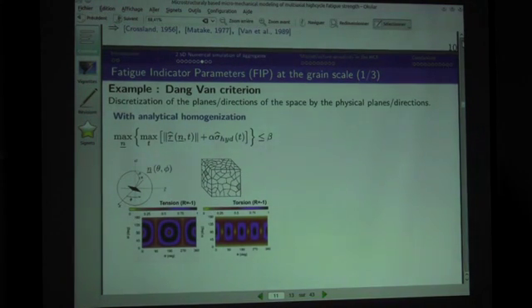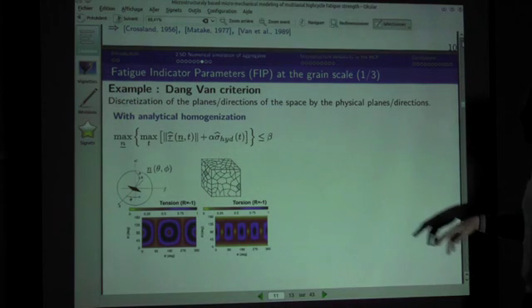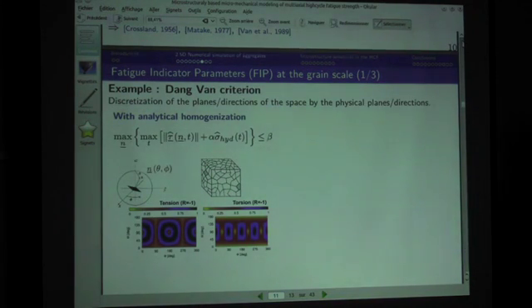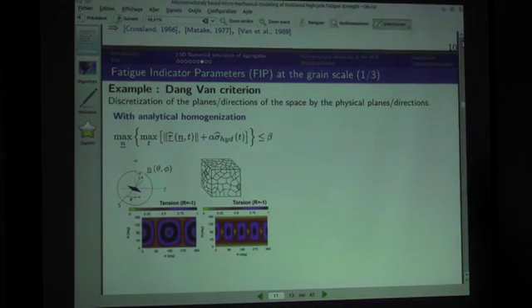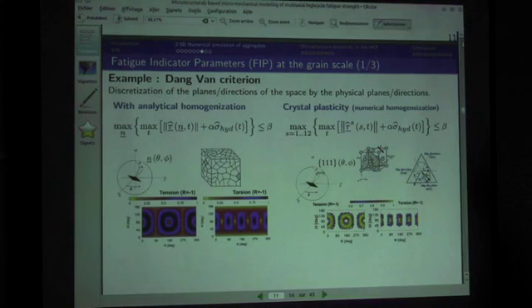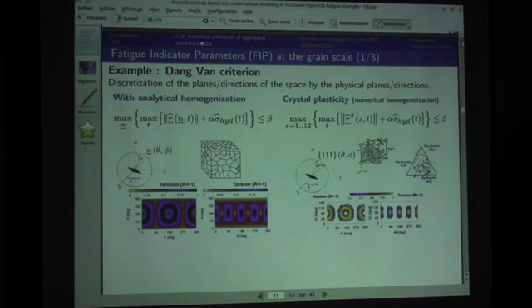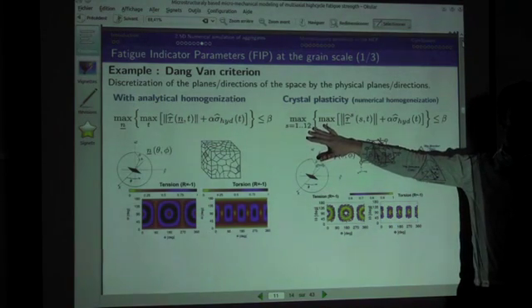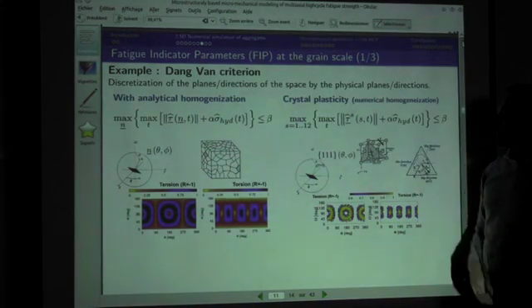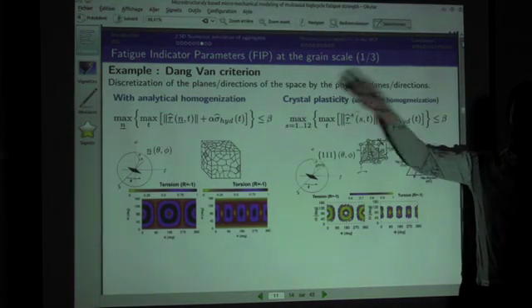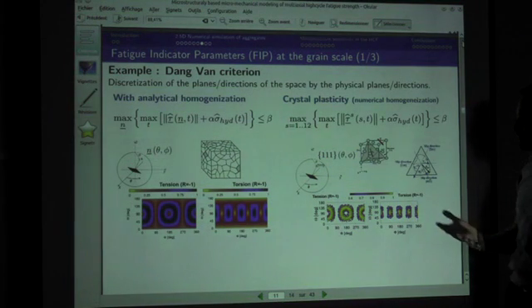Once we have the local stress and strains, how we use this, we choose different criteria. So here it's the Dang Van parameter, but you can use whatever you want for criteria. And what we are doing is projecting the criteria, the standard criteria, at the grain scale. So what we do is, as we did it for the constitutive behavior, instead of doing a screening on all directions over time, we are going to do a screening in each grain over the slip systems of the grain. And we keep, of course, the maximization over time. But in terms of space, we're going to limit the analysis to the slip systems, possible slip system of the aggregate,